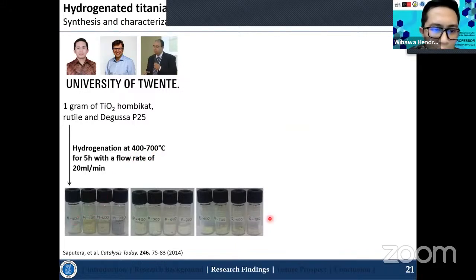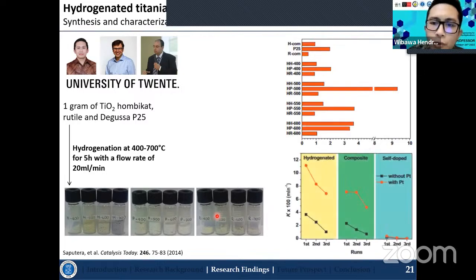So we can see that there are different colors generated, starting from yellow, white, yellow, and also gray colors. And P indicates P25, H indicates the Hombikat or anatase, and R is the rutile. So we can see in here that the HP 500 in these cases gives very promising photocatalytic efficiency. Compared with other catalysts, it gives very high photocatalytic activity.